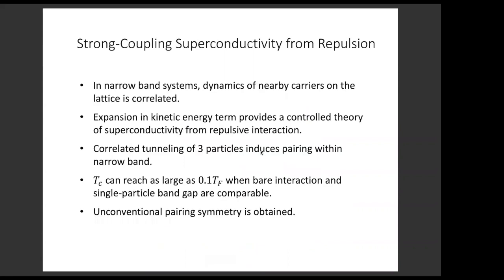So let me quickly summarize the theoretical results so far. We've shown that in narrowband systems, the motion of nearby carriers on the lattice will be correlated, so the effective hopping will depend on whether a neighboring particle is present or not. We developed a strong coupling expansion based on the kinetic terms, and this gives a controlled way to handle superconductivity from strong repulsive interaction. The correlated tunneling of 3 particles induces pairing within the narrow band. And Tc can reach as large as 10% of TF at low density when the theory is still controlled. This happens when the bare interaction and single particle band gap are comparable. And unconventional pairing symmetry, such as F-wave and spin triplet, is obtained. Next slide.